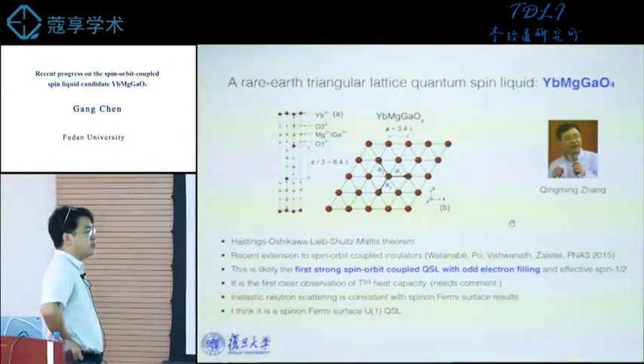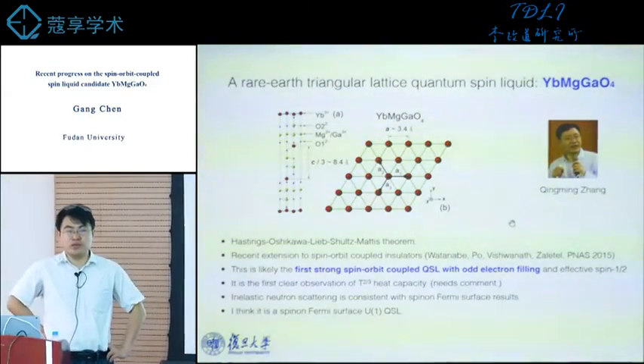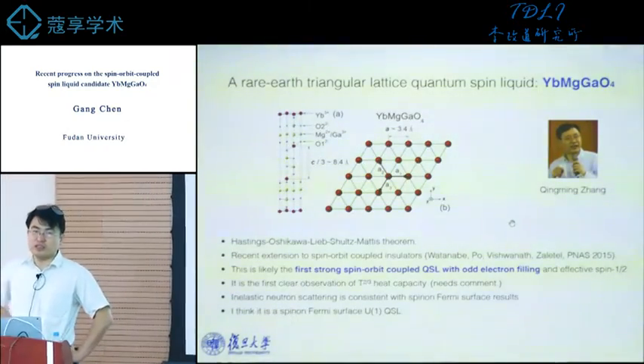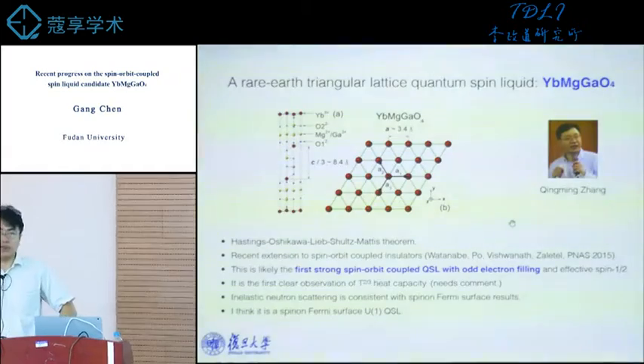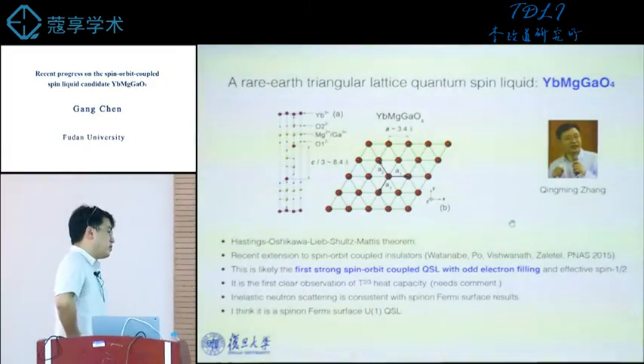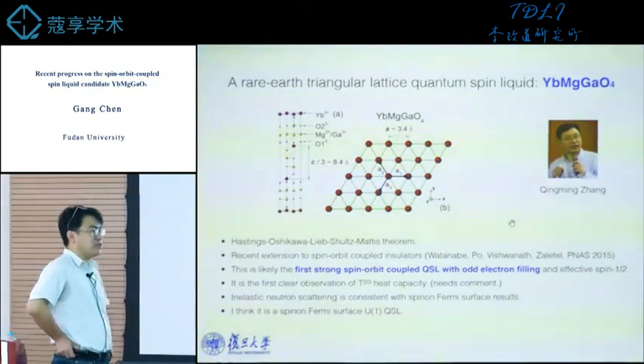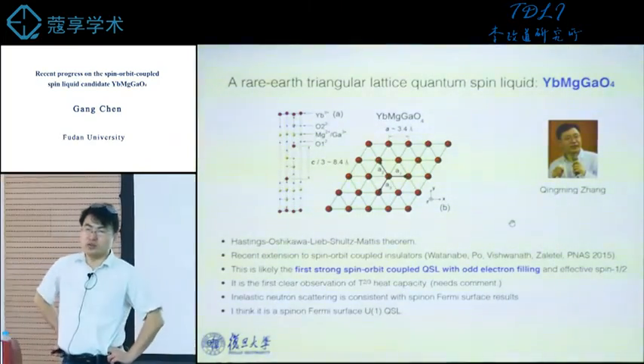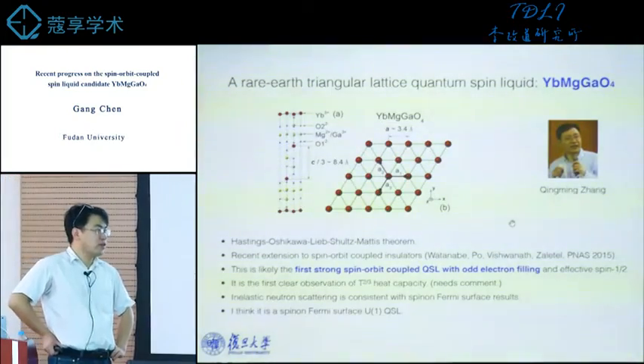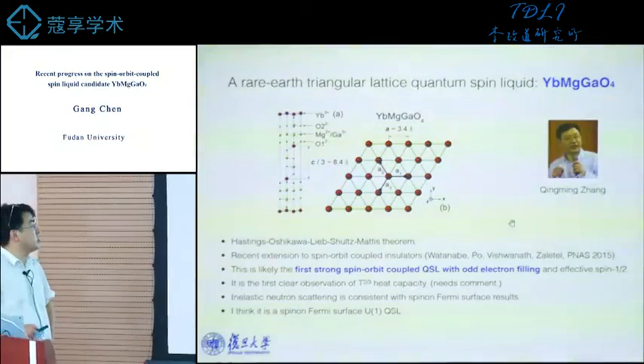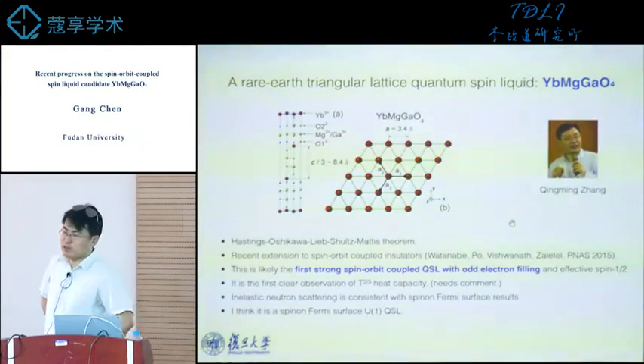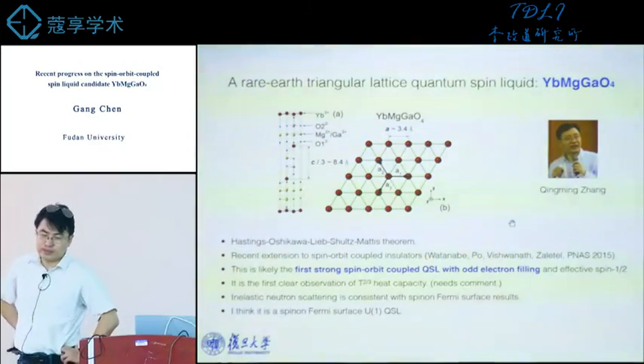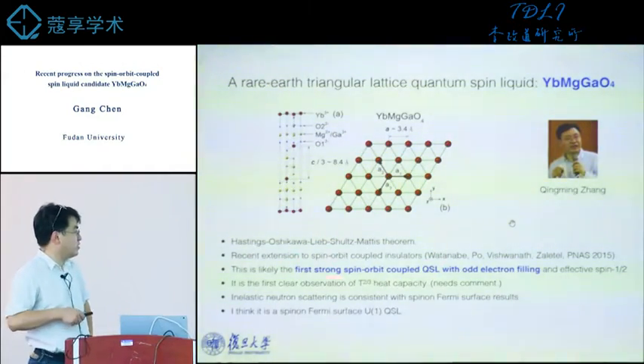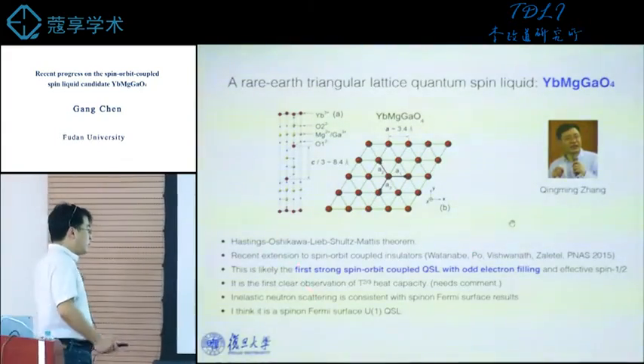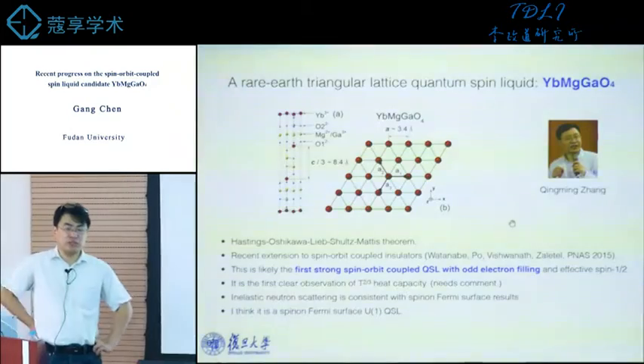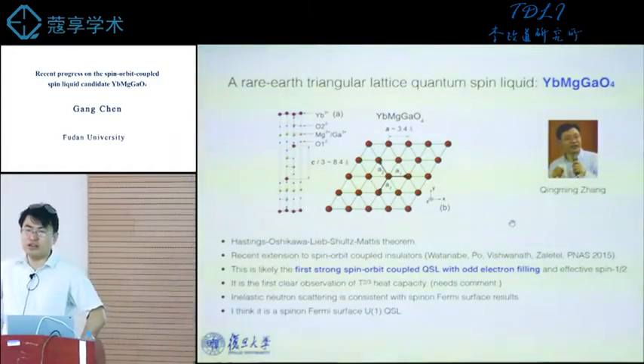If it is broken, it has to be broken at finite temperature, right? So in 1 dimension, it does not have to be at finite temperature. In 2 dimensions, there must be a finite temperature phase transition if time reversal symmetry is broken. So that means if you do any kind of measurement, you will see a finite temperature phase transition, you will see a Tc. But the thing is, time reversal symmetry breaking or any such phase transition is not seen in this material. So that means time reversal symmetry is preserved down to very, very low temperature. So then you can apply this recent extension. Since time reversal symmetry is preserved, the ground state of this material has to be exotic. So this is the underlying theoretical logic.